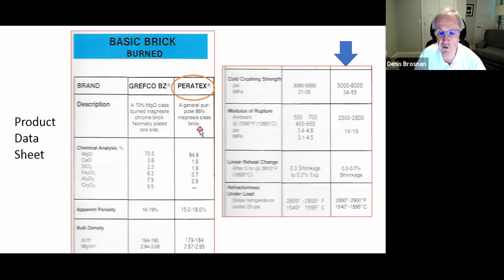But it's a 95% MgO class fired or burned refractory brick. And you can see, if you look closely down here, that it contains 94.9% MgO, a little bit of calcium oxide, 1.6%, a little bit of silica, 1.9%. Those are the fluxing oxides that help Peratex be burned and form a refractory material. A little bit of alumina, and maybe some traces of other materials. So that manufacturer is trying to show the chemistry to show that it meets a certain classification that was present at the time this product was made, published by the American Society for Testing and Materials.